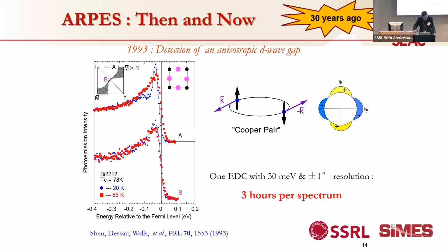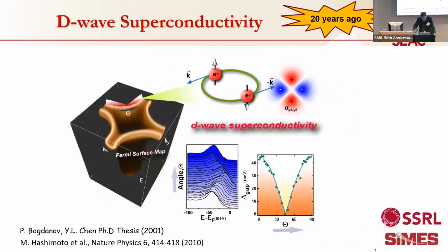That's 30 years ago, and 10 years later, now you can make a very detailed map, and you can see that the solid curve is the theory of the D-wave pairing structure, and the data points are very consistent. As I said, if this were an S-wave, there should have been a constant across with respect to angle.